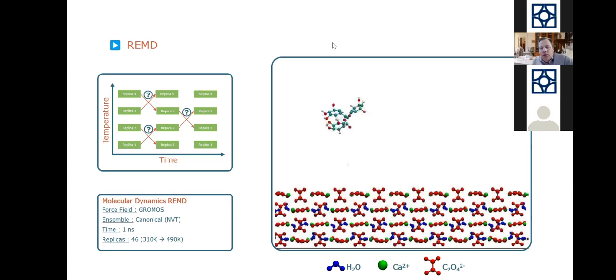Well, in the morphologies, we only look here at thermodynamics. You're right. At high temperature, it will be different, and we will then include the kinetics of the system. But we don't have the calculation power to do kinetic structure simulations on every orientation. If you want to model a morphology, we need at least 3 or 4 orientations, and this is a lot of work. I think it's not possible. So we only use thermodynamic data, and we correct them with the kinetic parameter. Did I answer the question?